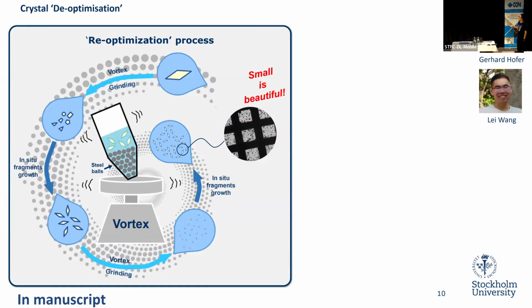You put in some seeds and then use the vortex and some beads to mill them into very small seeds. And then we add some protein back into the drop and hopefully grow some protein crystals at the same time as the next round of milling. So you're milling large crystals into small seeds, at the same time growing the crystals and recovering the packing in a way. And then we end up with very, very small crystals. And that's what we see on the grid.